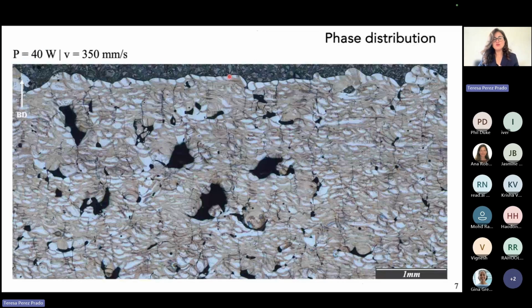But before that, I want to show you a little bit how these composites, crystalline-amorphous composites, look like. This is just a representative sample within this window. They all look similar. This is an optical micrograph, again, a cross-section parallel to the build direction. We have polished this surface and then etched it to reveal the crystalline regions. These dark brownish regions are the crystalline regions. If you look at the top layer here, you can see very well the melt pools. And you can see that these crystalline regions are located around the perimeter of the melt pools.